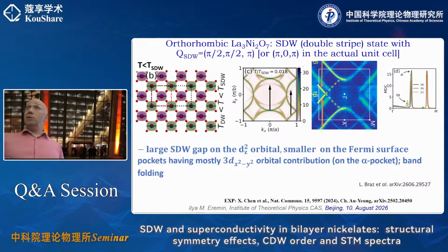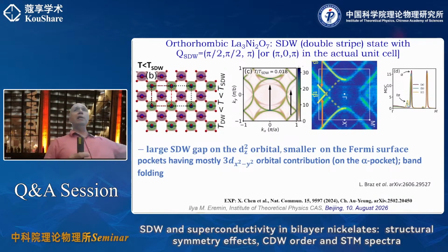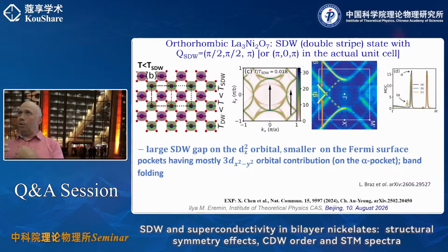Because you say, okay, there is a z squared, it's strongly correlated, it gives rise to some correlation effects, maybe spin density wave, but it's coupled with x squared minus y squared. The S plus minus symmetry of the superconducting gap mostly comes from the z squared, because it's an interlayer gap, and there is an interlayer exchange. So somehow there is an adiabatic transition from the weak coupling theory to a strong coupling theory. Somehow there are details, but there is an adiabatic continuation, in my opinion.